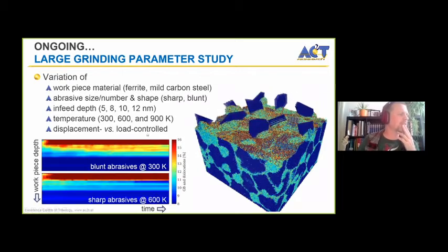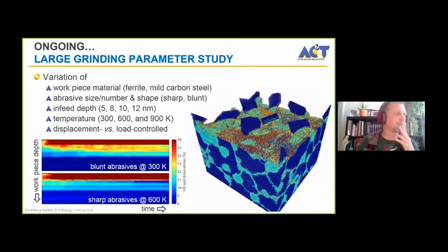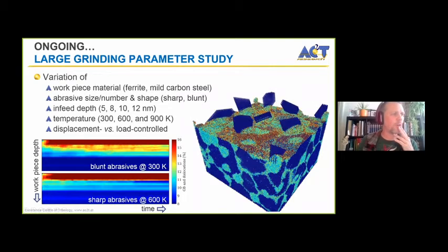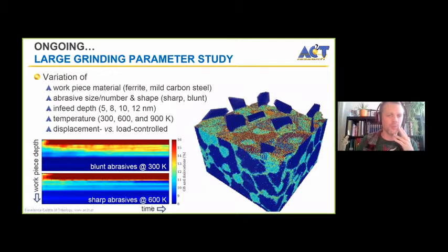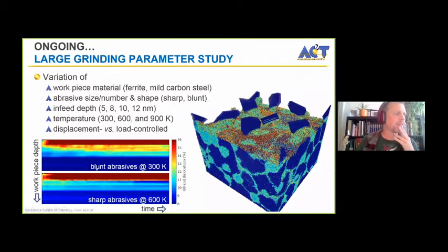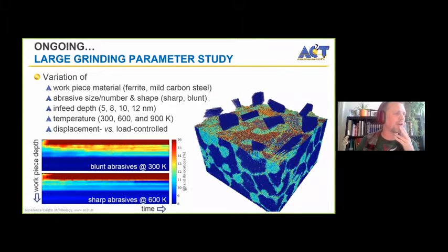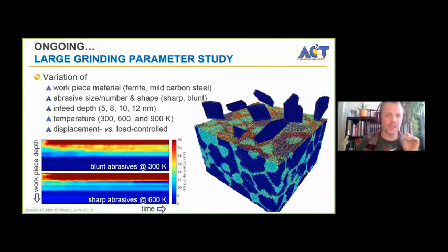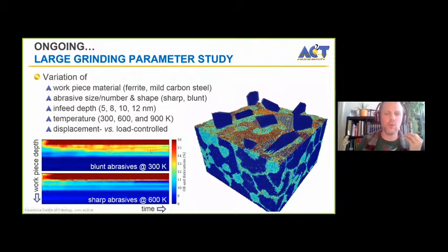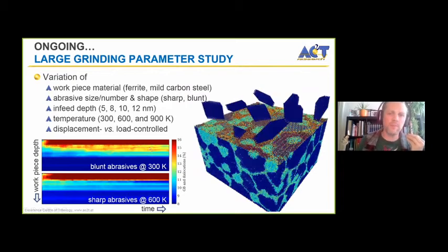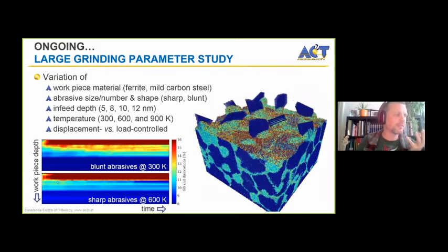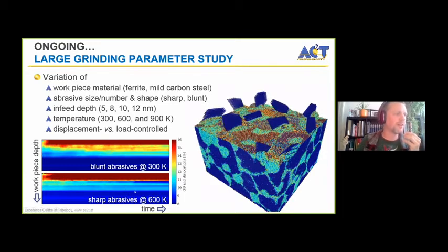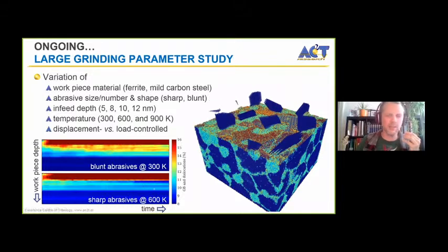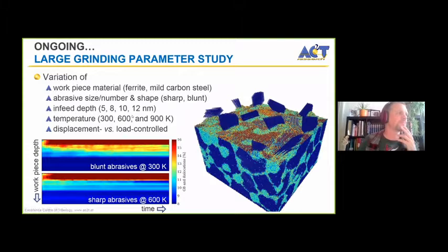I should be hurrying up, right? So just as a little example to see the difference, how blunt abrasives that are well cooled and sharp abrasives that are not cooled very well while they're grinding at the workpiece, how this changes the microstructure. What we see here is just a plot of the grain boundary and dislocation fraction in the system. And you see here that closer to red means more grain boundaries, more dislocations. It basically shows that these surface grains refine more, have more dislocations, may harden up. Whereas here with the sharp abrasives, the material removed is cut off, and due to the higher temperature, it actually heals out and we don't have any grain refinement here.